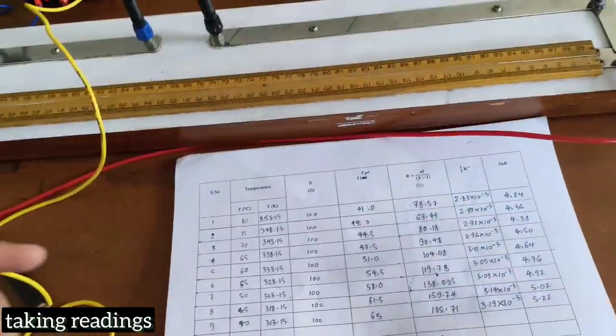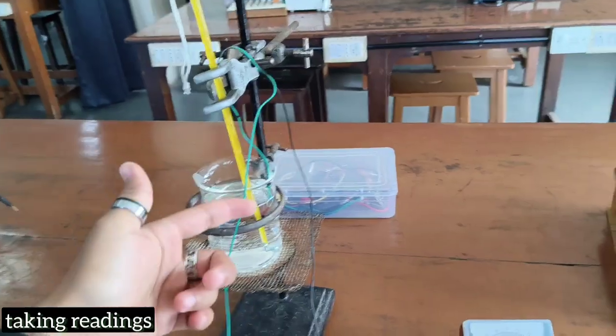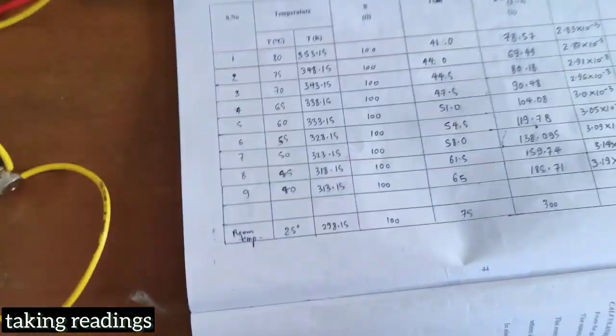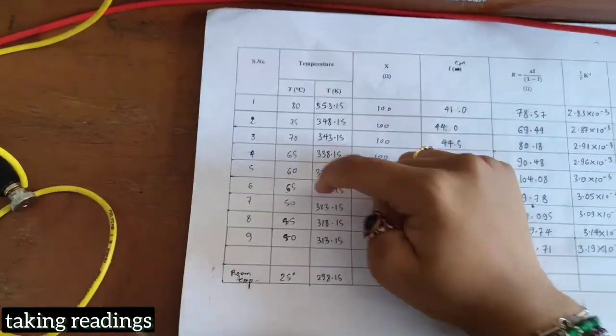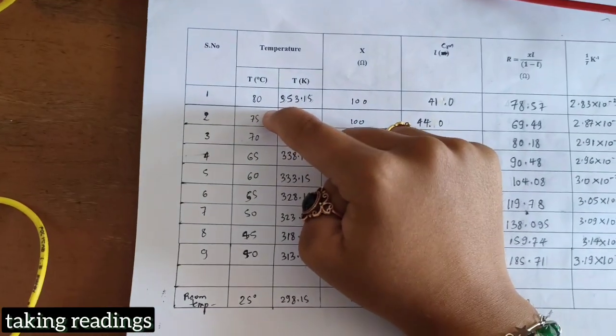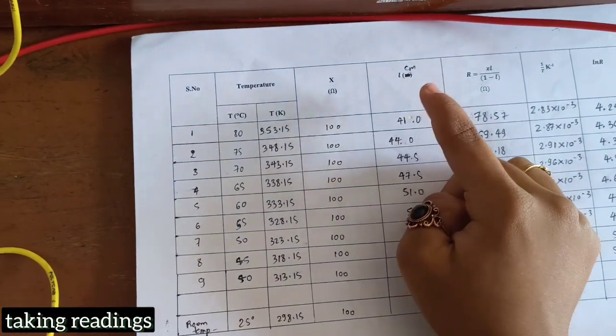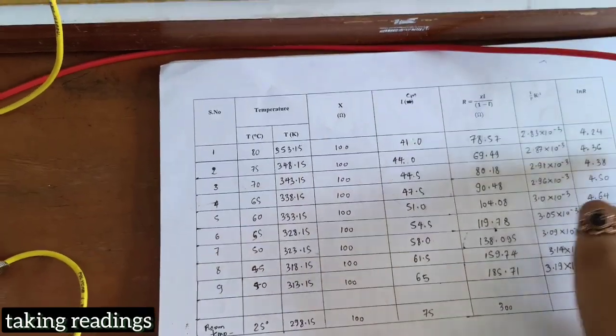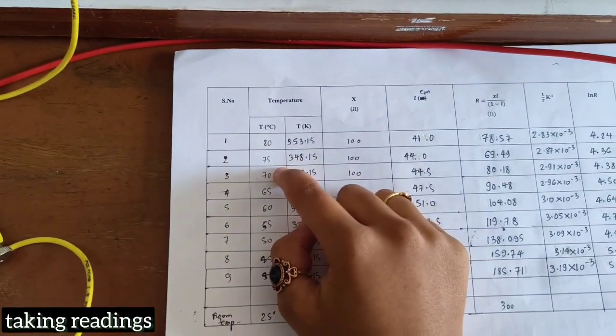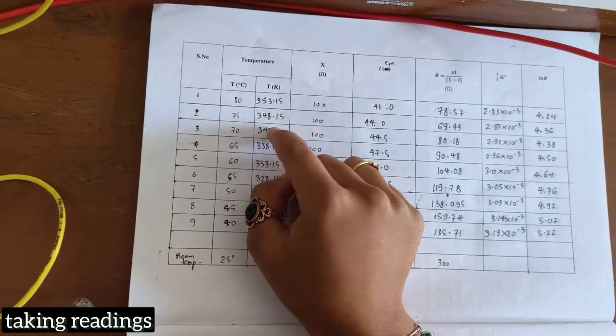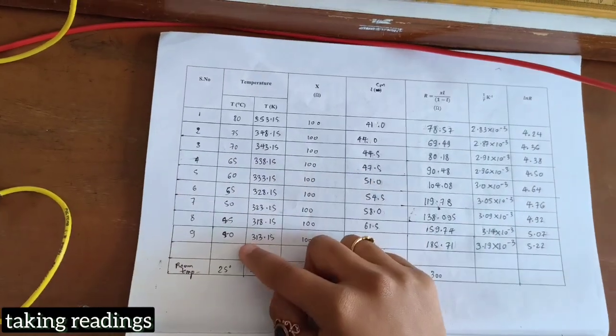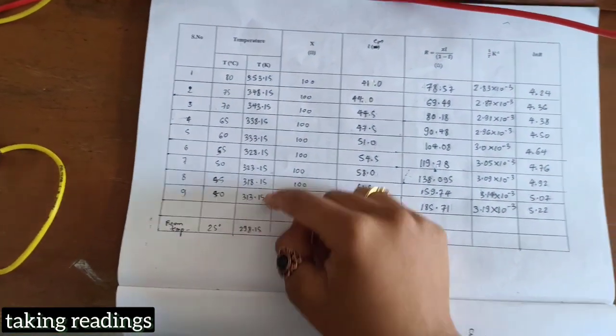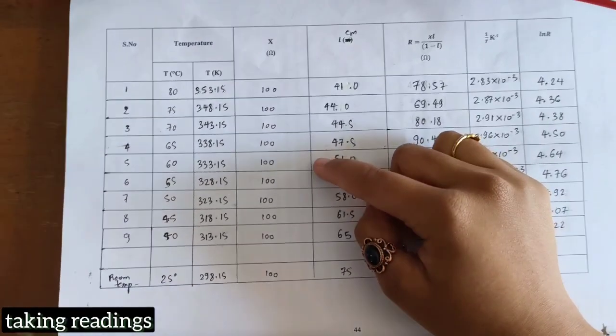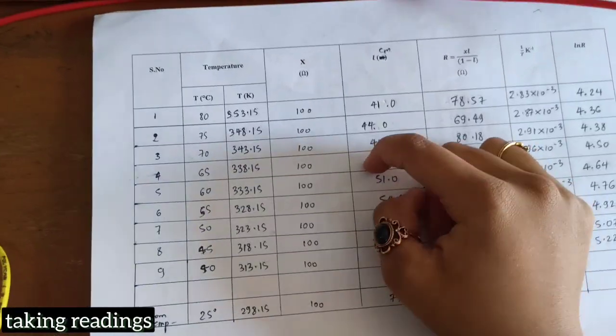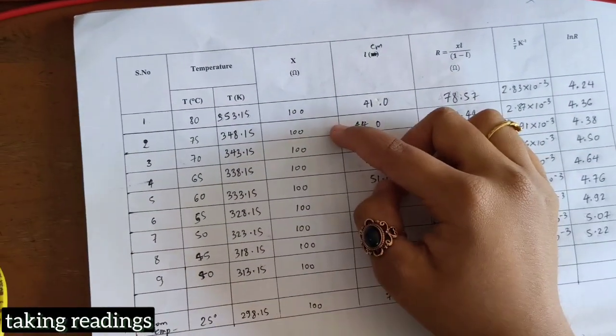Once that's done, you have to take hot water in the beaker. So the hot water will be at around 85 degrees Celsius or something. And so basically you wait for it to cool down to 80 degrees Celsius. Then for 80 degrees Celsius, you find the balancing length and do the calculations. Then wait for it to cool by 5 degrees and repeat it for 75, 70, 65 up to around 40 degrees Celsius. Then you convert to Kelvin, which is 273.15 plus the degree Celsius reading.